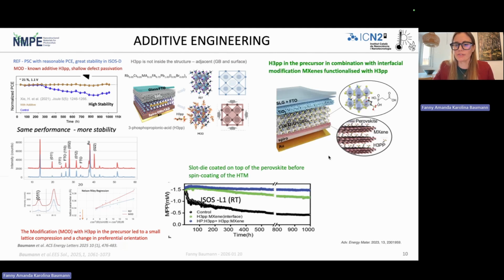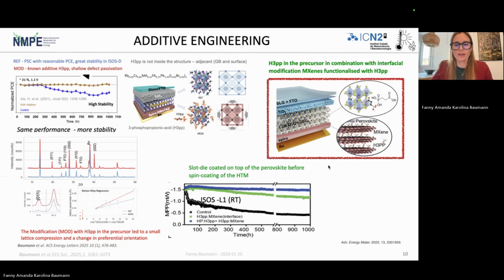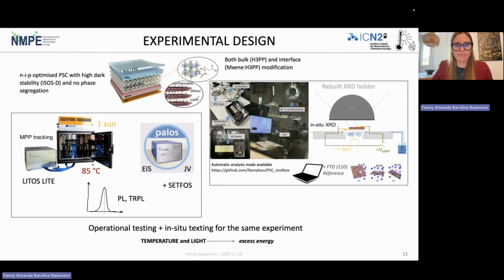And the second part is to add a MXene flake layer here, which are the laminated titanium carbide MXenes functionalized with H3PP. Then we seem to even further improve stability under illumination conditions. So this modification was not studied at higher temperatures, so we wanted to perform an extensive study at 85 degrees to see what difference we have with the stability enhancing modifications compared to the reference cell. Okay, so this is our modification.